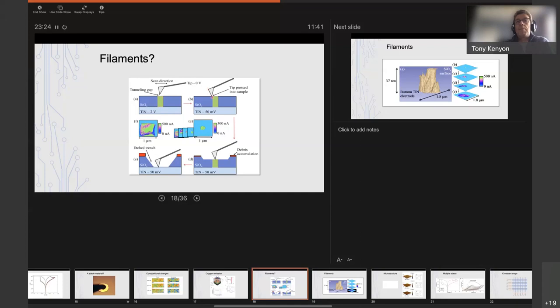Now, if that tip is very hard, and we can make this a conductive diamond, we can push the tip into the surface and we can actually scratch away the surface. And then we take another scan and we scratch away a little bit more of the surface. We take another scan and eventually we take slices through this material. And by stacking those slices on top of each other, we can reconstruct the region of high conductivity.